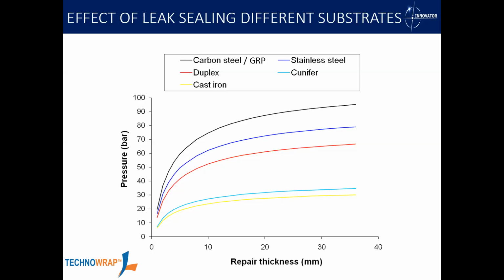But the key point is it's not whether we bond well or not very well, because cupronickel generally has much lower pressure seawater duties inside it, so it's not going to quite as high pressures. What's important is we've carried out the testing to establish the data for each different scenario. For every surface substrate type, we've done different levels of surface preparation, and we've tested our various repair materials on there. So if you come to me and require a design calculation, we have that data to back up the calculation itself. That information is very important when you're supplying engineered repairs.